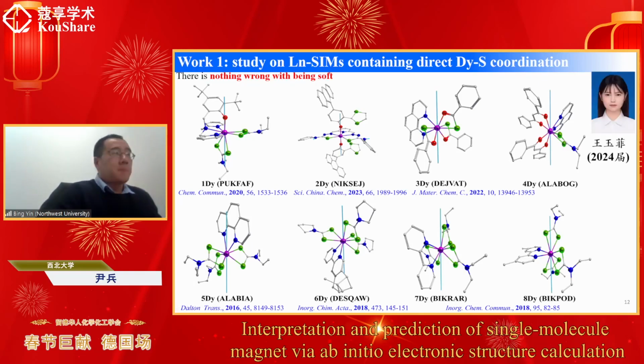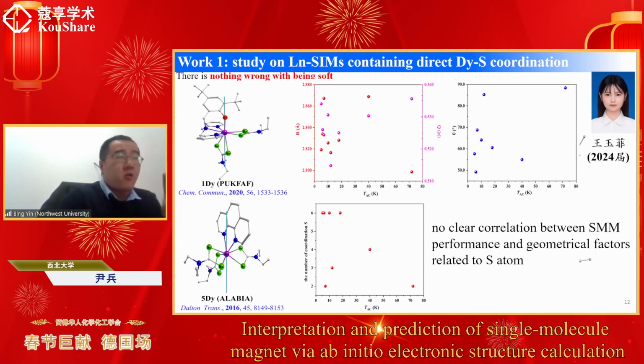But we found that there is actually no clear correlation between single-molecule magnet performance and the geometry factors related to the sulfur atoms. For example, the distance between the central ion and the sulfur, and the number of sulfur atoms in the system. So we think maybe more detailed theoretical studies should be carried out on lanthanide single-molecule magnet systems containing direct lanthanide-sulfur coordination.